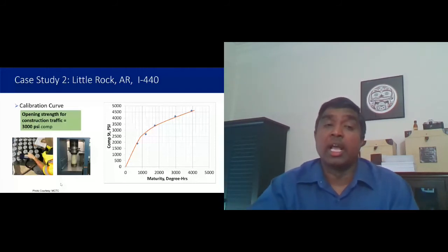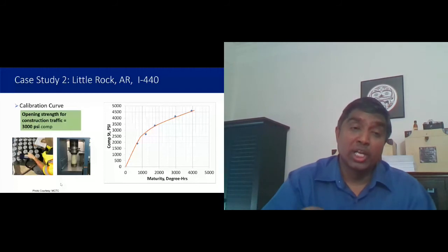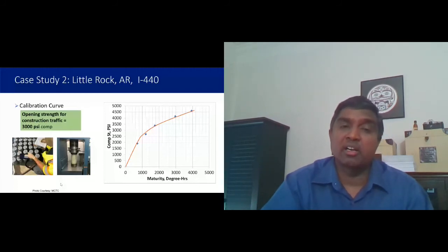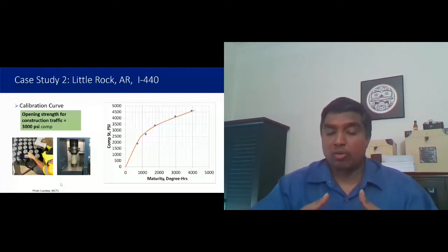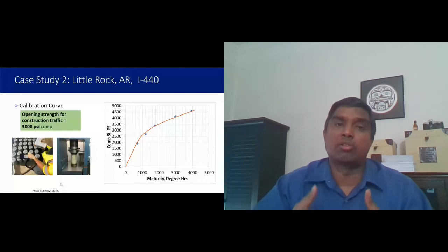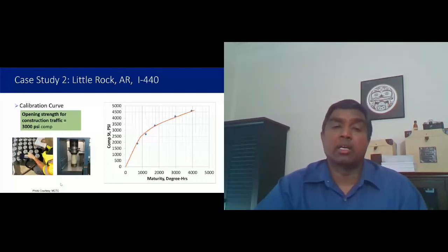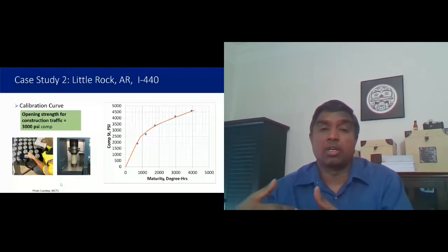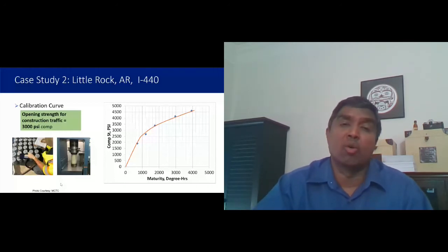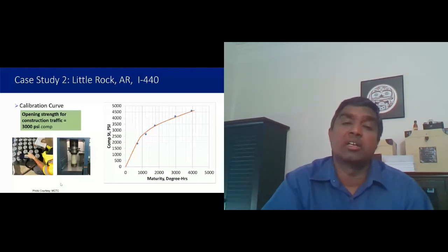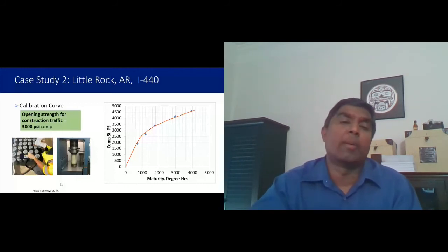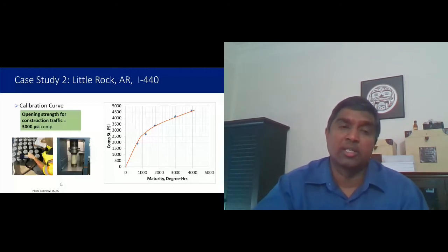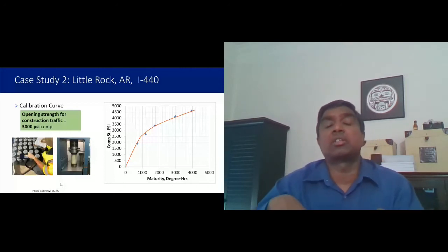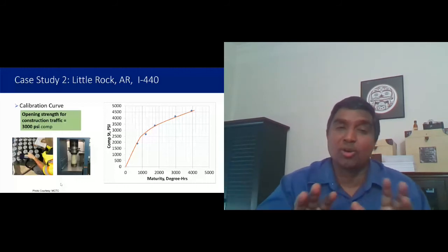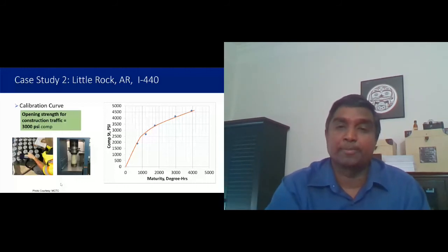of flexural strength. Now, one thing I do want to mention is you do see a bunch of cylinders there. I do not want you to misinterpret or think that we really need to make a lot of cylinders to do maturity. The answer is no. Depending on how you do it, you can get away with as little as 12 cylinders. But most people cast up to 15 cylinders. The cylinders you see in that picture are also used for other purposes. So just want to mention that.